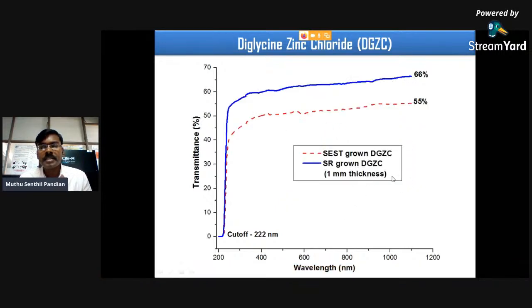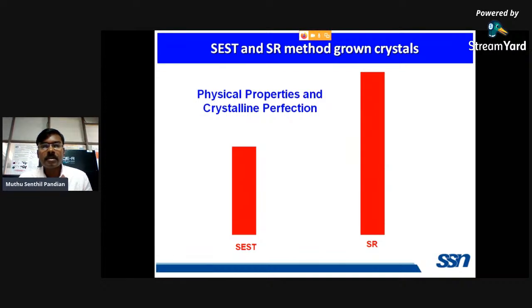So this is again UV-Vis, a comparative statement. The final conclusion for the conventional and SR method grown crystals: because of the micro cracks, milky opaques, low angle grain boundaries, and growth center boundaries, their physical properties like mechanical stability, UV-Vis, optical quality, and electrical permittivity of the conventional method grown crystal are less comparable to the SR method grown crystal.